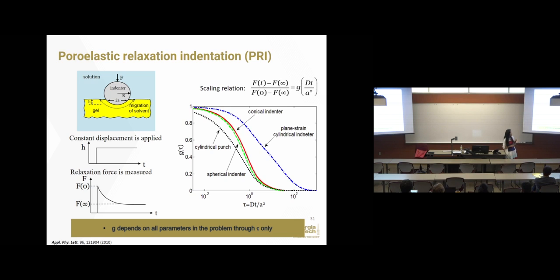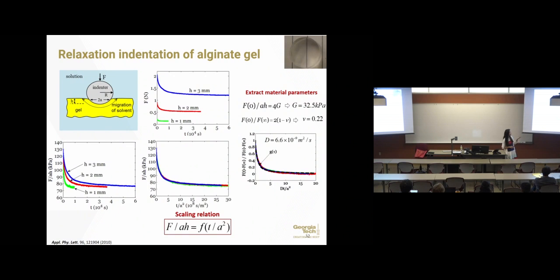And so the curve you see here is the master curve. It's only different for different shapes of indenters. So from now on, people don't have to do numerical simulation anymore. They can just use this curve to get material properties. And for ease of use, I fit it with a continuous function so people can directly use it to extract material parameters. So here is one set of early experiments I did, applying this indentation relaxation on alginate gel.